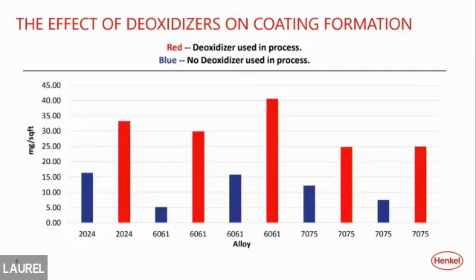So we only have a limited time in these systems. If your throughput is a problem, if you're ramping up production and you need to get more parts, more capacity through your systems, this becomes an issue if you're not hitting your coating weights. And you need to dial in your deoxidizer and make sure that you've removed that surface so that your conversion coating isn't doing the work of your deoxidizer. Because my conversion coatings, being I work with aluminum a lot, are acidic and will do a bit of etching.